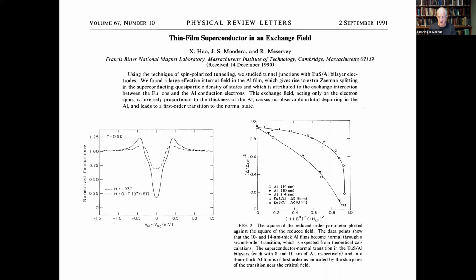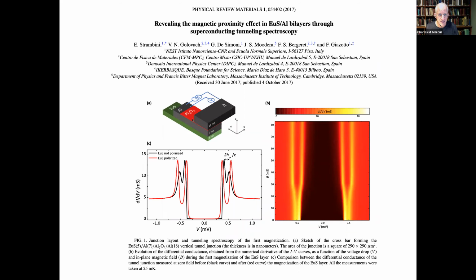So now moving from here in 1991 up to 2017, and the work from Strambini working in Francesco Giazotto's group in Pisa, with these material collaborators, including Jagadish Moodera, the same guy growing those films, sees this, and now a kind of cleaned up version of the data, a couple of important features. This is now the same material, europium sulfide, in a tunneling experiment with thin aluminum, tunneling across an aluminum oxide barrier into a thicker piece of aluminum. And what you can see is that this, again, Tesla scale exchange field, which splits the density of states, can be recognized. And there's two features that I want to point out.